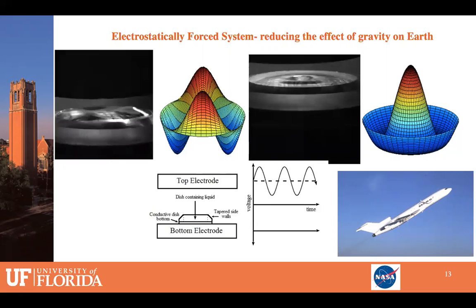Now, an interesting thing is that an alternating electrostatic voltage selectively reduces the effect of gravity. Now, it will not completely eliminate gravity. It will reduce the effect of gravity, bringing out the effect of surface tension. If you wish to bring out the effect of surface tension even more, you can take this experiment on a short duration microgravity flight, such as on a parabolic mission. And this is a project that we have proposed and which we will be running on a parabolic flight, where we will be comparing our measured frequencies and patterns and make that comparison with results that we will get on ground.